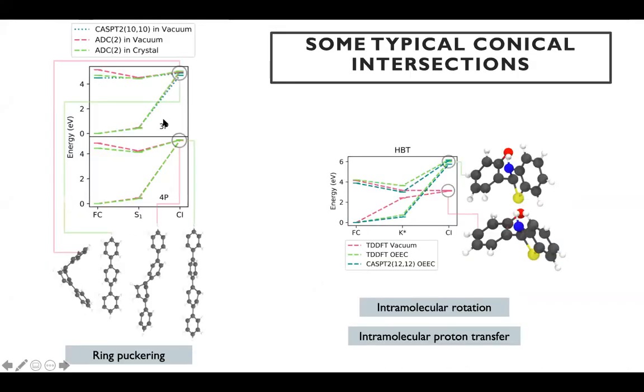So just to show you some typical conical intersections for some of the systems, and here illustrating some typical aromatic systems where you have a set of aromatic rings that can just pucker or can rotate around a single bond. And you can see that for these systems, you will have an increase of the energy of the conical intersections when you go to the solid state. Again, this is related with this cage effect that you will have in the solid, and also because of the interactions that the molecules can establish with the molecules that they have around.